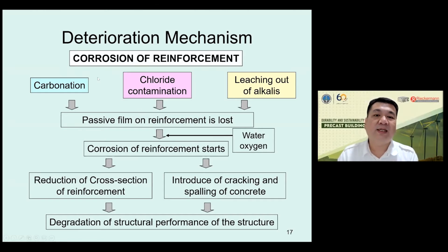But sometimes the pH of the concrete is reduced by the action of carbonation and leaching out of alkalis, and also some chloride contamination can destroy the passive film. With the availability of water and oxygen, the corrosion of the reinforcement will start. Once corrosion starts, we have two types of degradation. One is the reduction of the cross-section of reinforcement, and the other is the cracking and spalling of the concrete. Overall, it will cause degradation of the structural performance of the structures.